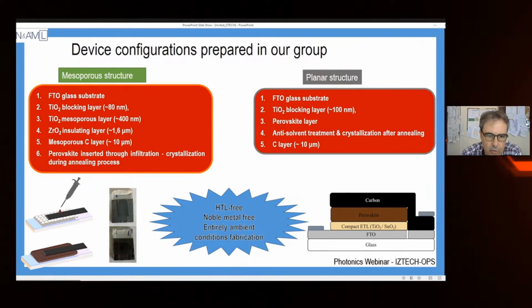And then, as you can see here, we can put the perovskite within the pores of the material, finally with an infiltration method, and finally we heat the substrate in order to crystallize the perovskite. So after we put the perovskite, we put it also in an oven just to crystallize, and we follow this annealing process. The temperature that we use for the devices depends on the kind of perovskite that we use.